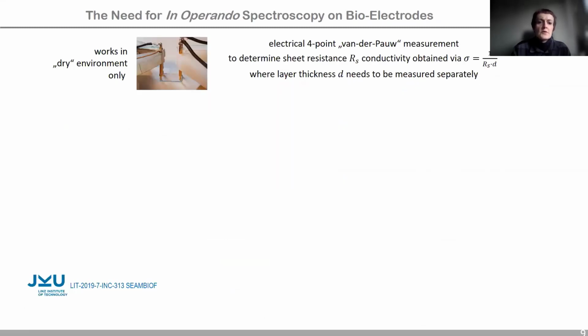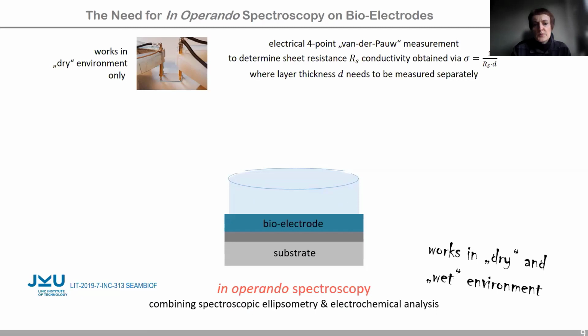This brings me to the methodological aspect of the project, which is the in operando spectroscopy of solid-liquid biofunctional interfaces. Typically, the conductivity of a thin film electrode, such as an ITO electrode, is measured by the conventional electrical van der Pauw method, which could not work in an electrolytic environment. Our in operando spectroscopy approach works under dry and wet conditions and provides multiple information simultaneously. It combines optical spectroscopic ellipsometry and electrochemical analysis.